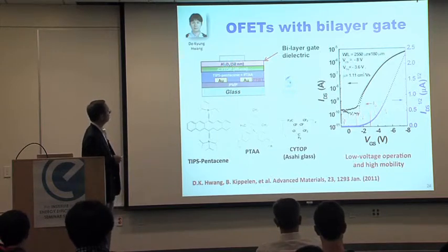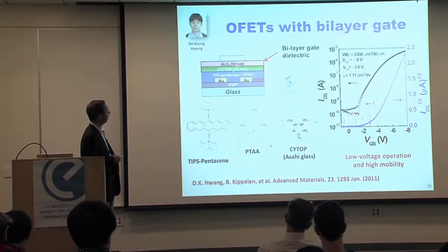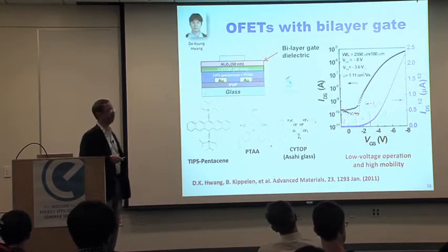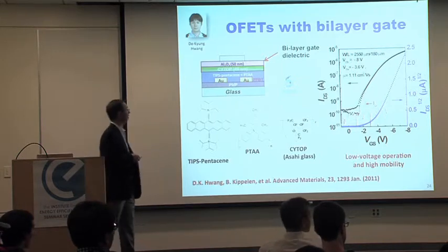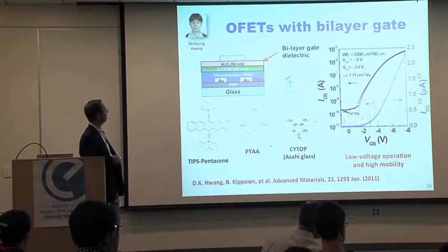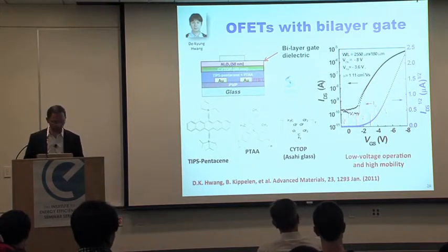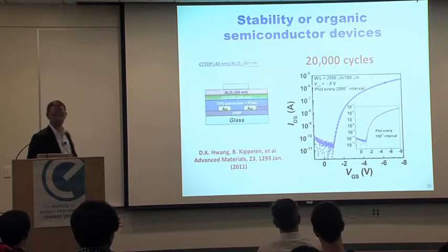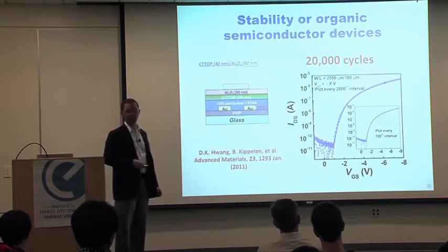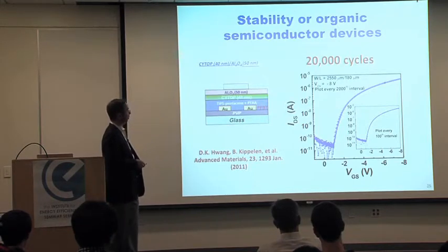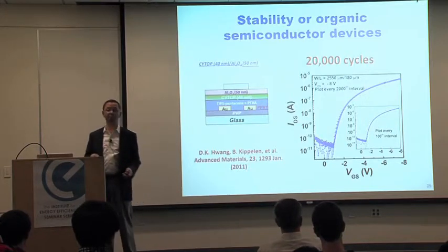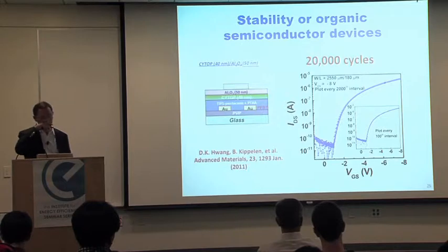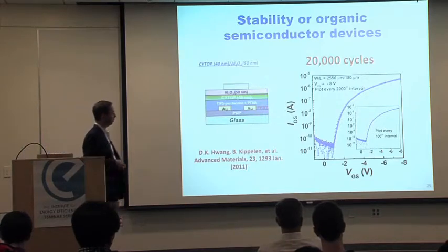But if you grow another thin layer of aluminum oxide on top of that thin layer of Cytop, you get something that has a relatively high capacitance density of the order of 30 to 35 nanofarad per square centimeter. And so you can get transistors that have a fairly low operational voltage. But what really surprised us was the stability of these transistors. Here's first the stability on cycling. You can see 20,000 cycles, and there is no shift in threshold voltage. There is no degradation whatsoever in the performance of these devices.